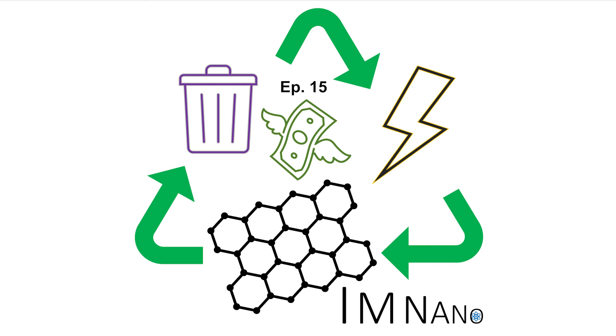They say the surface of the sun is approximately 5,000 Kelvin or approximately 5,500 Celsius, 9,900 Fahrenheit. So you're looking at half the heat of the sun in 10 milliseconds. That heat applied can fluctuate depending on the source material and the compression of the material between the electrodes, but we are breaking the chemical bonds overall with a lot of energy. That allows the carbon atoms to rearrange themselves, and then the other atoms that are not carbon can be evaporated or sublimated away, such as water — leaving pure graphene. It's amazing how we're using all these older techniques and models to solve current problems.